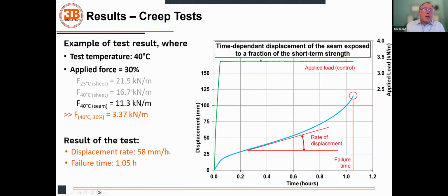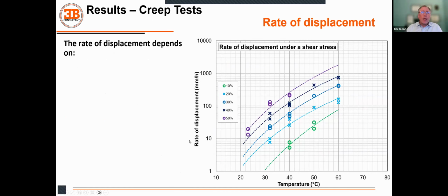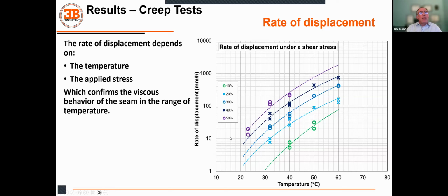And what do we get? A displacement rate that we can measure here, that's the slope of this curve, and a failure time, which is the time at which we have no continuity left. So the two panels have split apart, they're no longer connected together. We tested all these conditions that I've shown you, and we got this cloud of data. I would say the numerous data connecting together the temperature with a rate of displacement, with a variety of percentage of the seam strength.